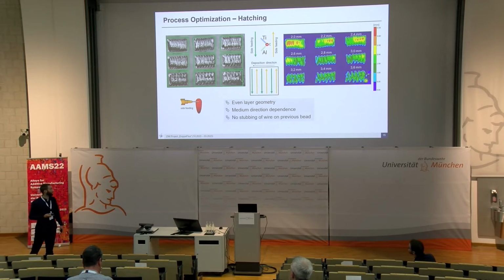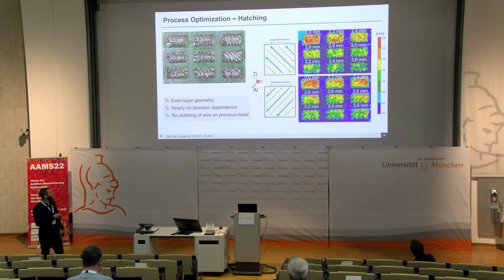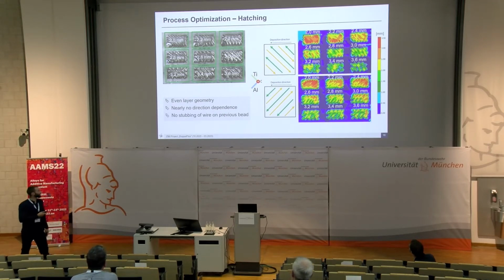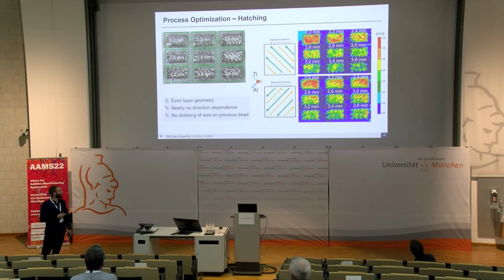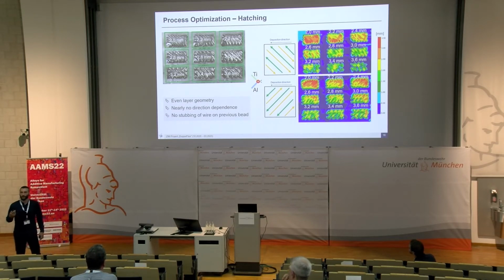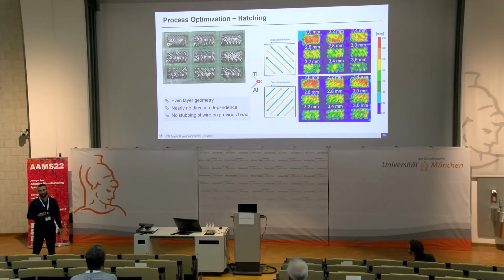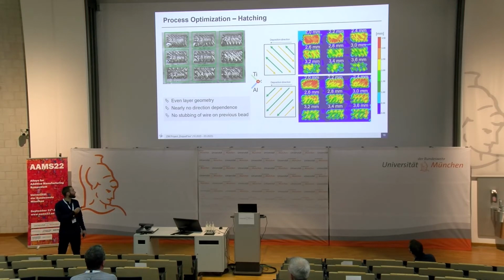Lastly, we did a 45-degree hatching. We see we also have even layer geometries, especially when we alternate these two directions. We can get a really smooth and really even layer geometry. We also have nearly no direction dependence of the simple tracks, and we have no stubbing of the wire on the previous bead. So we decided on a hatch width of 2 millimeters and the 45-degree hatching.